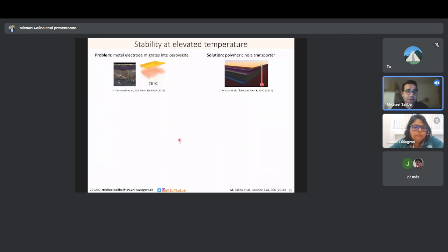Okay, stability, of course, one of the big concerns. So here, two different strands of thought entered. First, we discovered that the spiro-OMeTAD hole transporter was permeable to metal transport upon heating. So this means although the perovskite may be stable, the surrounding layers could cause a problem. Second, by using a polymeric hole transporter, although it didn't give high numbers, it was clear that it hampers the metal transport, so it cannot leak into the perovskite layer, destroying it. So then this gave the idea of combining the best performing perovskite at the time, which was the rubidium-based perovskite, together with a high performance polymeric hole transporter.